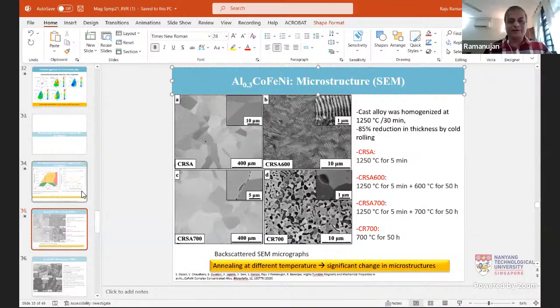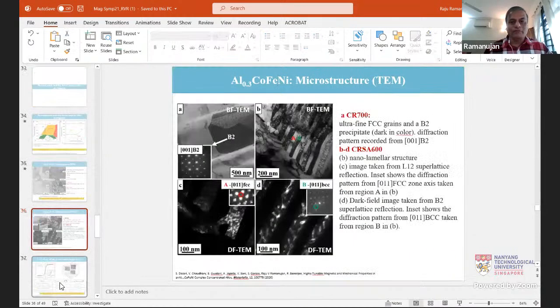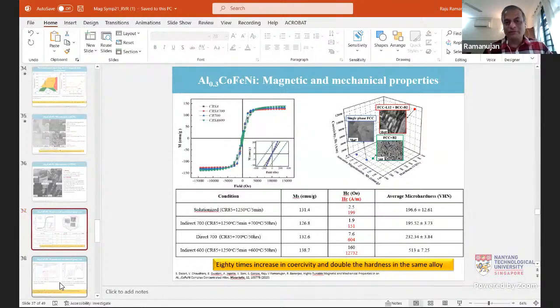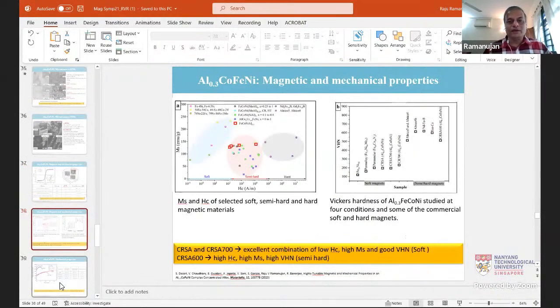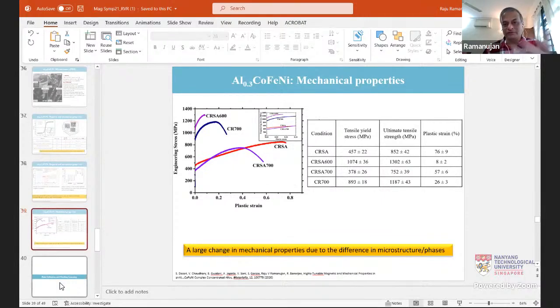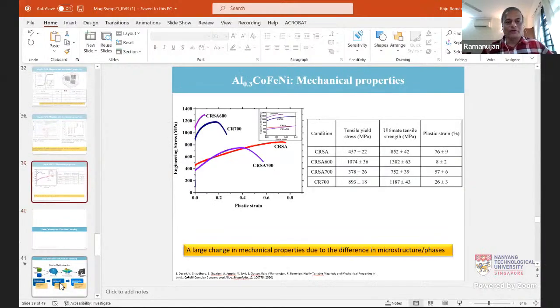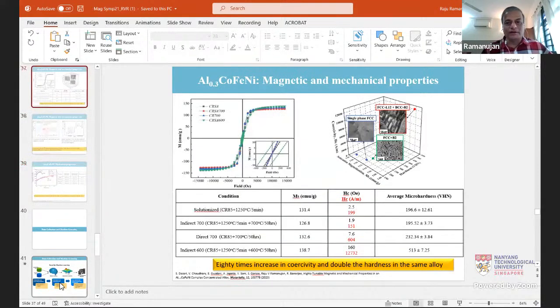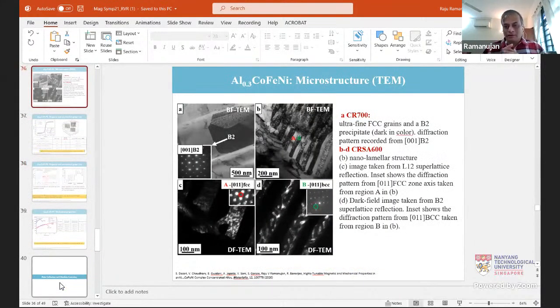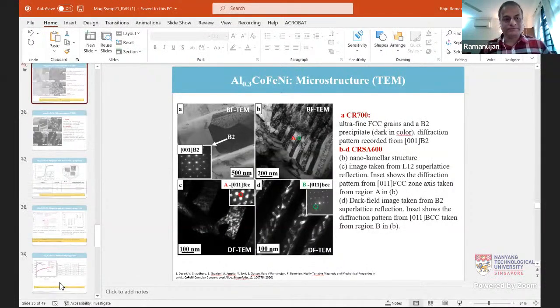So we've looked at this system, and we've done magnetic properties, we've done mechanical properties, and compared this to the literature. In this case, we did it in more detail. We did actual stress strain curves, so you can see some of the results that we obtained. Exactly what you said is correct, that the microstructure is very fascinating and is very much related to the classic Alnico, but it goes beyond Alnico as well, because we are using this large composition space as exploration.